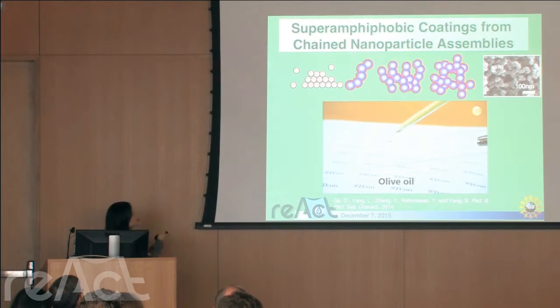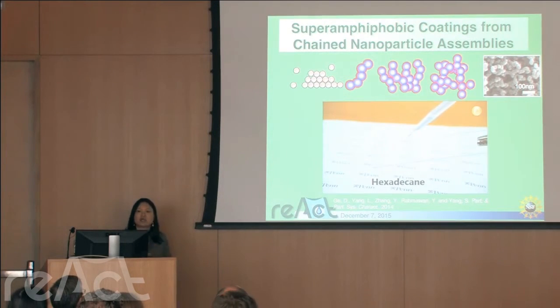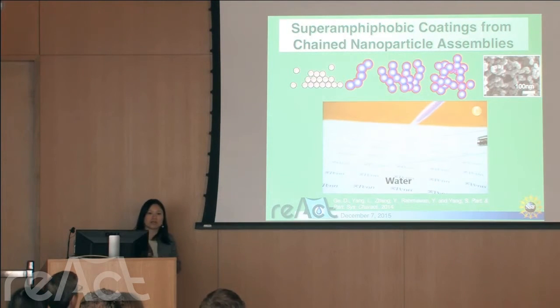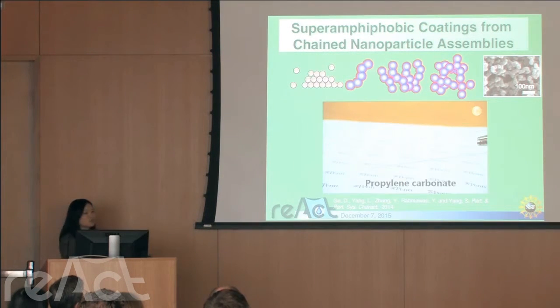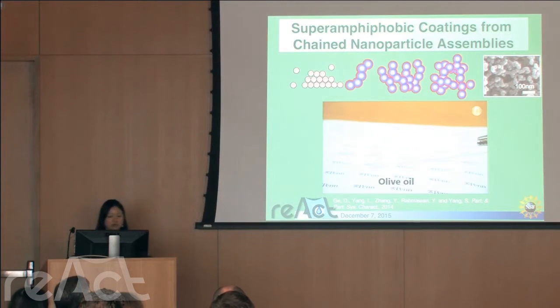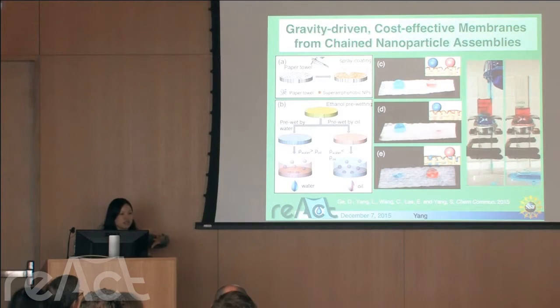Because of increased porosity compared to spherical nanoparticle assembly, we generate fractal surfaces which can prevent oil wetting. So not just super hydrophobic, it's super oleophobic. We call it a super amphiphobic surface. So controlling the porosity, utilizing different morphologies of the nanoparticle, is critical. And because they form this mesh, right? They form a network.